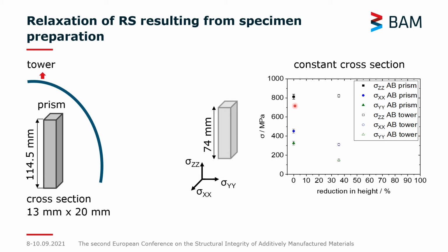And we see that our stresses in the build direction remain fairly constant, whereas the other stress directions are relaxed. So despite the fact that we reduce the height by 35%, we only see a very small effect on the build direction.